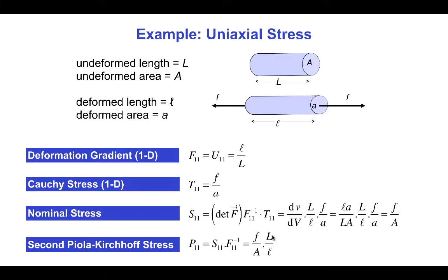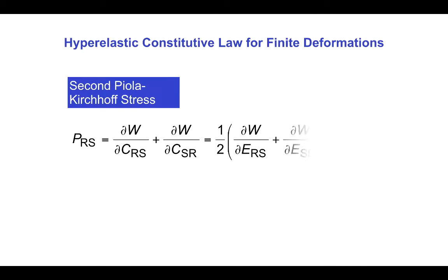So if we want to write the constitutive law as a function of Lagrangian strain components, we should use it to evaluate a Lagrangian stress in which both components refer to undeformed coordinates. So by analogy with our original derivation of the constitutive law for hyperelasticity, we can show that the equivalent for finite elasticity is the second Piola-Kirchhoff stress, P, determined from the derivatives of the strain energy, W, with respect to